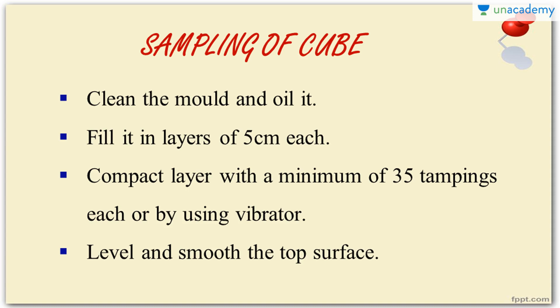Clean it thoroughly, dry it, and oil it. Now fill the concrete mix in the cube mold layer by layer — each layer should be 5 centimeters thick. Each layer is compacted with a minimum of 35 tampings using the tamping rod, distributed uniformly in the concrete matrix. Continue until the entire mold is filled. If you have the chance to use vibrators, please do so, as you will get very consistent compaction of the concrete mix.